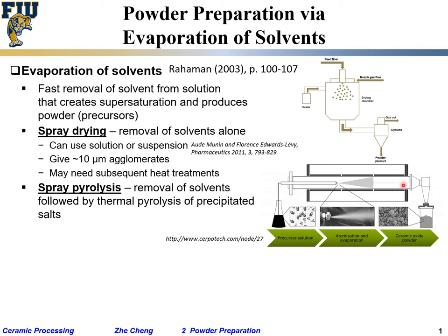This is the setup for spray pyrolysis. Quite often it's done in a tube furnace type of setup. On one side you feed either a fine uniform solution or a colloidal suspension, then use atomized high velocity gas to break the liquid into small droplets. The high velocity gas carries the liquid droplets through the furnace. A nozzle sprays fine droplets — a mist — into the heating chamber inside the tube, going through solvent evaporation and some chemical reactions.